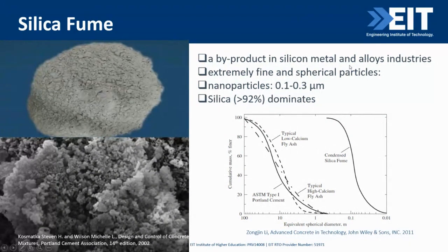The mean size of silica fume is 0.1 to 0.3 micrometer, which is about 100 times smaller than that of Portland cement and many other mineral admixtures such as fly ash. So the benefits of extremely fine nature include high activity resulting in high surface areas and the ability to pack between cement particles inside concrete. Of course, such fine particle sizes of silica fume also have drawbacks in handling and significantly higher water demand.